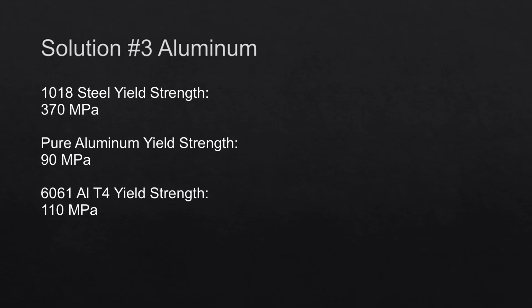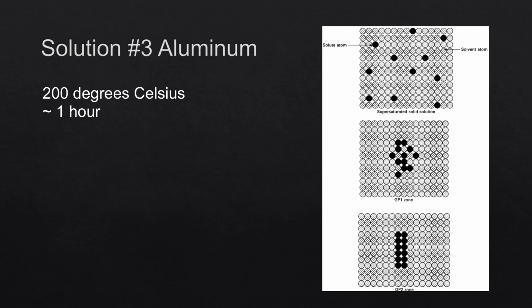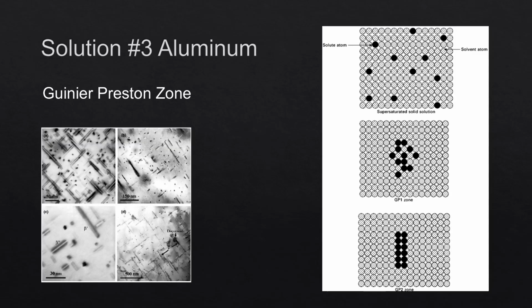The metal then goes through thermal age hardening at roughly 200 degrees Celsius for 1 hour. Because the concentration of the alloying elements are higher than the equilibrium solubility, the solutes will diffuse to form clusters, assisted by vacancies within the aluminum lattice structure. These are called GP zones, short for Guinier-Preston, and are usually 1 to 2 atomic planes thick and range from 10 to 50 nanometers in length.